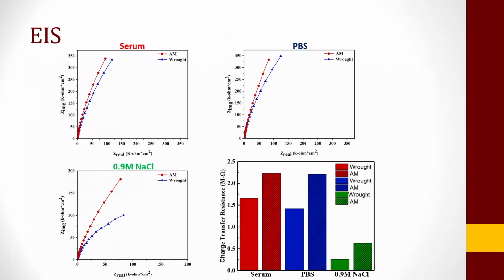Similarly, when we look at electrochemical impedance spectroscopy, you can clearly see that whatever the medium is, whether it's a blood serum or the PBS or the 0.9 molar NaCl, the semicircle for additively manufactured is bigger than that of the wrought, which basically tells you that it is much more corrosion resistant in these mediums as compared with the wrought.